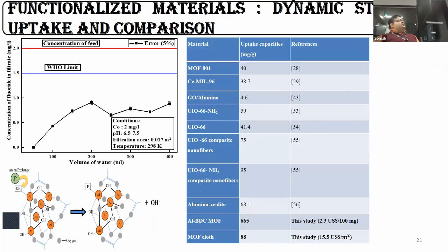We carried out another dynamic study using a vacuum pump and filtration apparatus, where this MOF filter paper can be attached, and continuous flow of fluoride-laden solution was taken into account. The feed concentration was nearly 2, higher than 1.5. Over a span of time, we obtained 400 ml of filtered water using that small filter paper, where the filtration area is around 0.017 meters square.